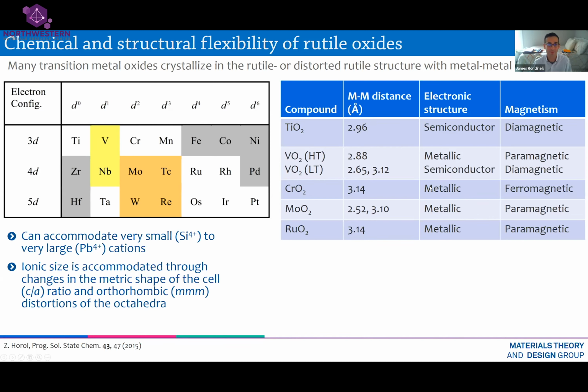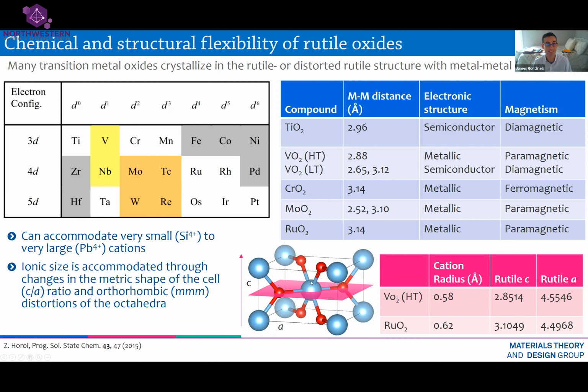So very few changes need to happen as I change, say, the size of the cations that are accommodated in this structure. So vanadium dioxide is the one I've been talking about, and vanadium has a particular radius, 0.58 angstroms. Ruthenium has a particular radius, 0.62. And what you can see is that in this rutile structure, when I make the substitution of vanadium with ruthenium, the major change in the structure is the C lattice constant, how long the lattice constant is along this direction of the unit cell. The A lattice constant, the one in plane here, doesn't change very much. It's fairly similar. The major change is the one along the out of plane direction. And so the structure is very flexible in that sense.